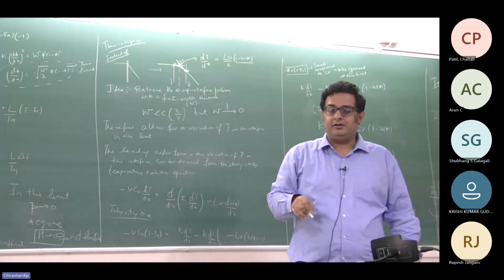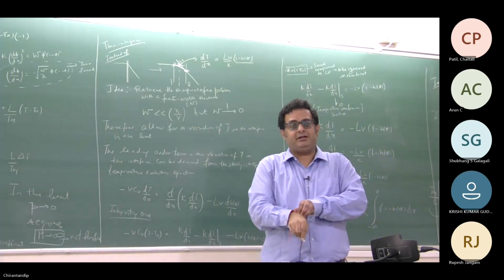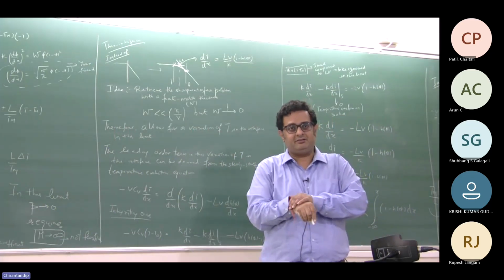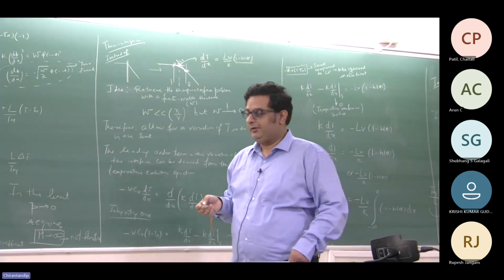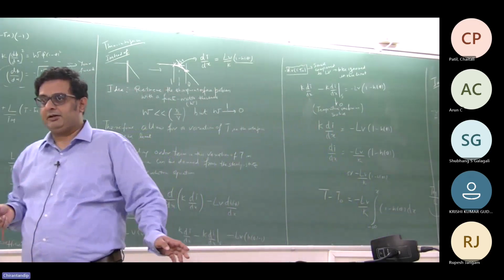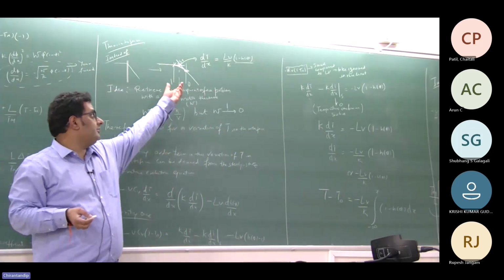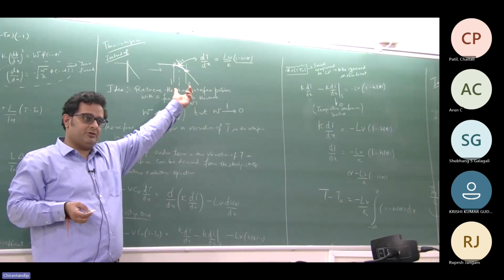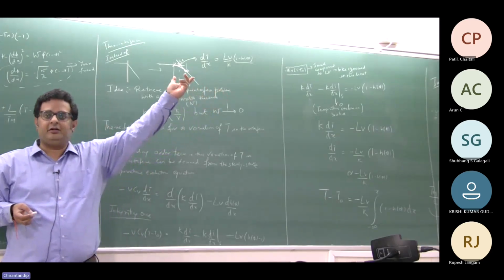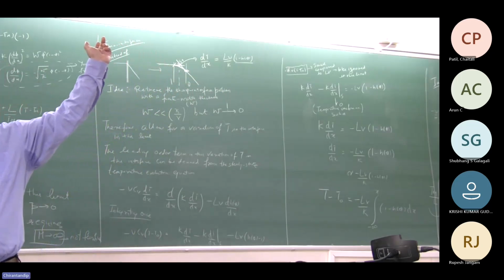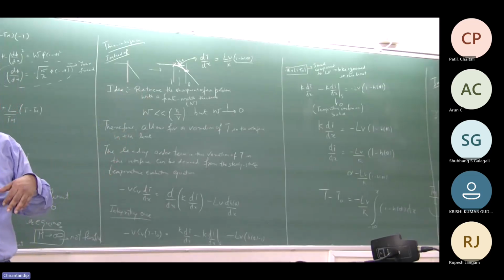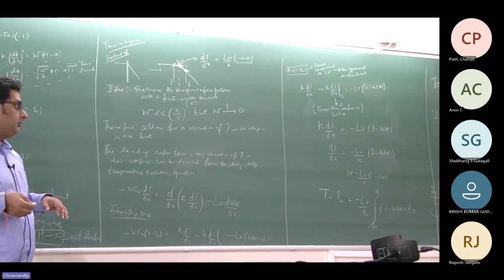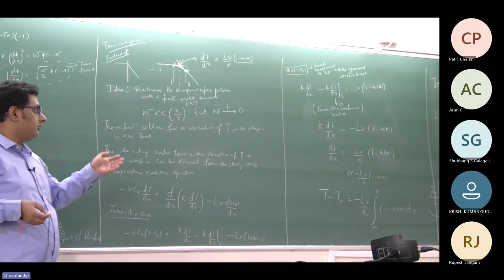So how do we take care of this? As I remarked yesterday, the trapping that typically happens in experiments at higher speeds is a physical one. It's a solute trapping effect. We typically don't want to get rid of it. However, you are essentially having trapping over here because of a diffuse interface width, which is much larger than the physical one. And therefore, it's an artificial effect to that extent. So we need to correct for that, because you are having trapping at speeds where in experiments we do not have it. To make comparisons with realistic experiments, therefore, we need to correct.